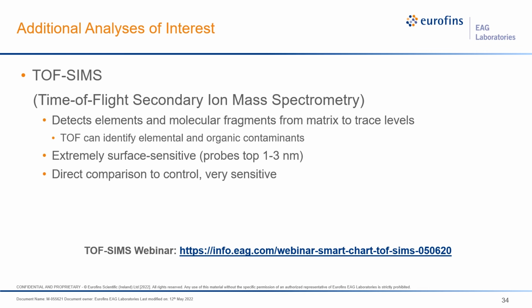But say you saw a fairly clean sample, but you are extremely sensitive to any contamination, you may want to do TOF-SIMS to see if there's a more trace contamination. Or if you were very, very concerned about the amines that we saw in the FTIR and the nitrogen we saw in the XPS, and you want to know more about that molecular structure, we could use TOF-SIMS to look at that. Again, there's also been a webinar done on TOF-SIMS, and there's the link right there.